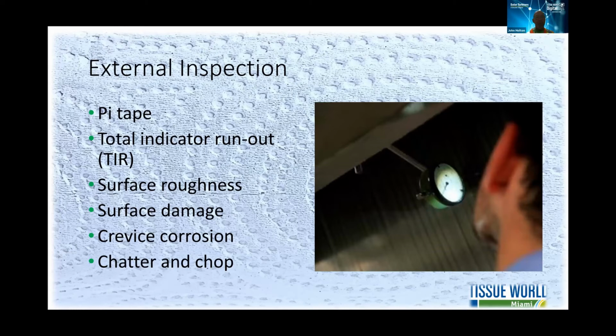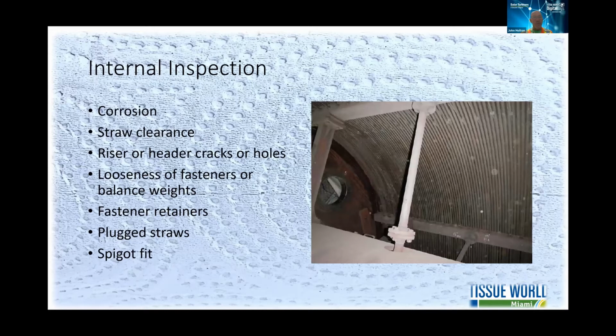But the external inspection, that would include pi taping, total indicator runout, or TIR, surface roughnesses, mapping of surface damage, inspections for crevice corrosions, chatter, or chop. The next common inspection is an internal inspection, where you might check for corrosion, straw clearances, riser or header cracks or holes, looseness of fasteners or balance weights, fastener retainers, plugged straws, or spigot fit.